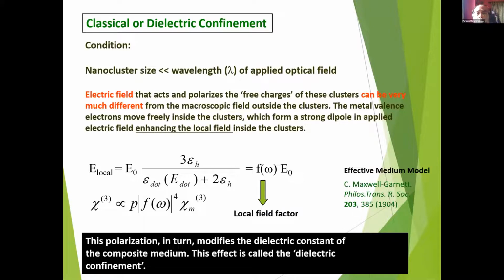See, this is the classical confinement, where the metal particles are extremely small compared to the wavelength of light incident on the metal particles. Then the electric field acting on and polarizing the free charges of these clusters can be very different from the macroscopic field outside the clusters. These metal valence electrons move freely inside the clusters, forming a strong dipole in the applied electric field and enhancing the local field inside the clusters. That means the local field inside the clusters is very different from the macroscopic field occurring in the entire medium. I'm talking about a host medium like the glasses, and the metal particles suspended in the glasses.